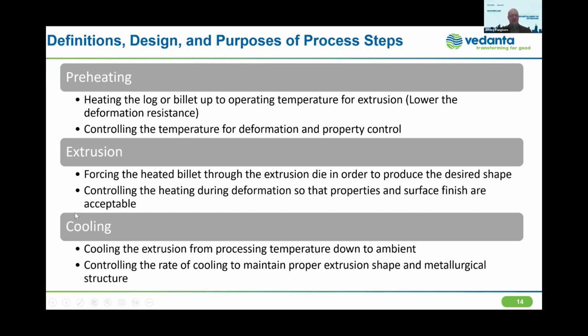Extrusion, of course, this is our main forming process. We have the heated billet. We're pushing it through the die that we chose to produce something for our customer. But it's really important to control this and make sure that we're well above the temperatures that are critical. So the 500 C range that we threw out there is the high end of the critical temperature range, because actually some particles will begin to form in preheating that we do not want, some large Mg2Si particles, but in extrusion we have the opportunity to absorb that.